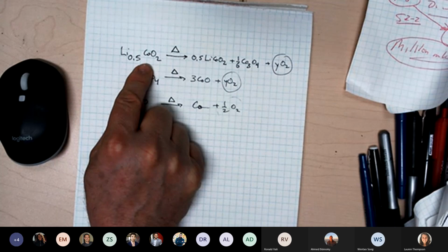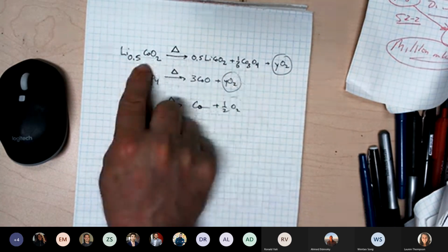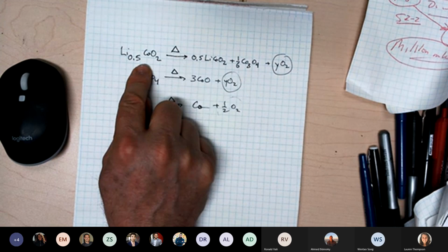If you just take lithium half cobalt oxide and do thermogravimetric analysis on it in argon, it doesn't thermally decompose like this until probably around 200 degrees C. But in the presence of a reducing agent like the electrolyte, meaning the organic solvent can combust, that helps to strip the oxygen out and drive this reaction at lower temperature.